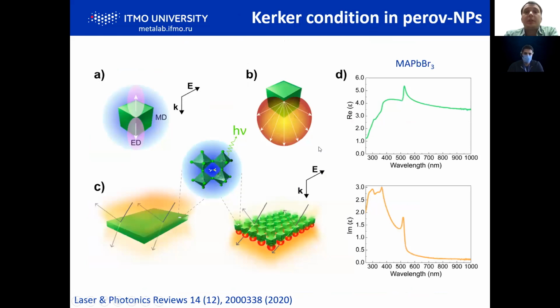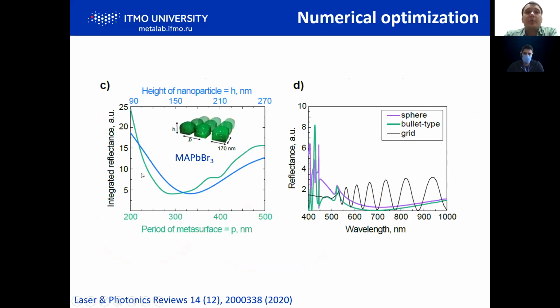And as I told you already, in dielectric nanoparticles we can achieve so-called Kerker conditions, when we have interference between magnetic dipole and electric dipole resonances. Let's assume that we have a cubic particle, and we can achieve forward scattering in each particle, and then we can create a metasurface based on these Kerker nanoparticles demonstrating Kerker effects. So we considered a standard bromide perovskite with a pronounced exciton also in the visible range. We performed optimization calculations for a metasurface made of these perovskite nanoparticles.